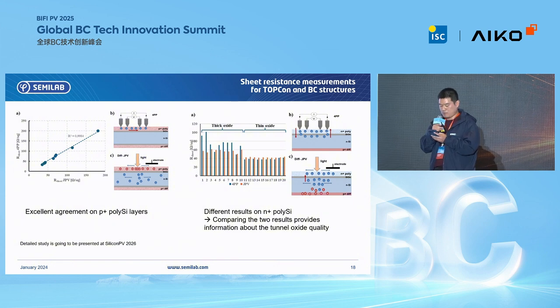This page is about the sheet resistance. We know and have already applied these non-contact techniques, the JPV method, in PERC and HIT cell structures. But what about the doped polysilicon layers in TOPCon and BC cells? Our recent research proves that the two methods correlate pretty well in the case of P plus poly layers on N-type wafers, say on emitter-type junctions. In this case, the space charge region below the polysilicon layer isolates the polysilicon layer from the substrate. So both measurements, the contacting 4pp way and the non-contacting JPV method, are sensitive only to the top layer, whose sheet resistance is our interest.